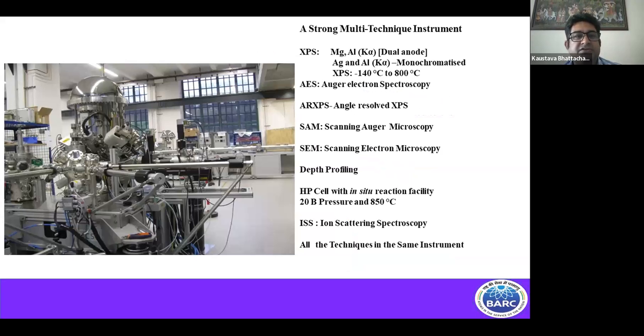So this is the tool in my lab. Here you have a dual anode source. We can do Auger electron spectroscopy. We can do angle-resolved spectroscopy. We have a scanning electron microscope. We have a scanning Auger microscope. We can do depth profiling. We can do in situ reactions in a cell, and we can take the XPS. We can do ion scattering spectroscopy.